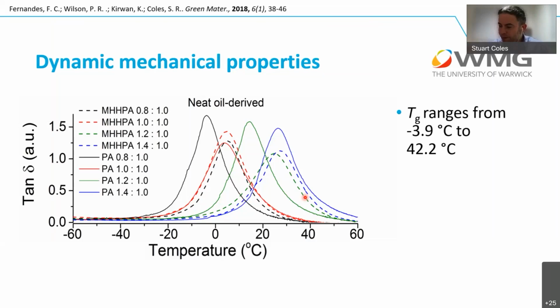We tried because we wanted to see if it was possible, but the reality is that we're putting a plasticizing polymer into an epoxy network, and that is going to reduce the Tg. And we couldn't really avoid the physics in that situation. That vegetable oil chain, which is quite bendy and flexible, means that it lowers that glass transition temperature. So we knew that we had to think a little bit about the application and where we were headed at that point.